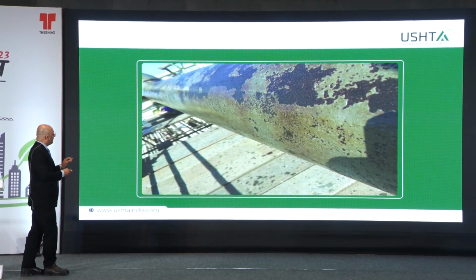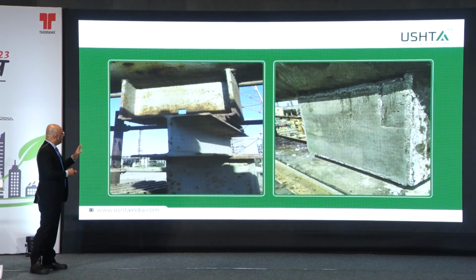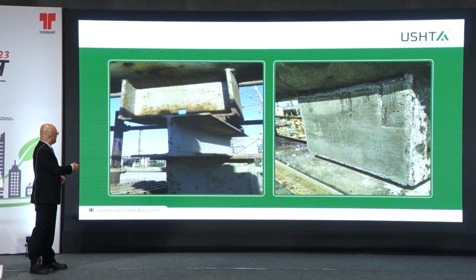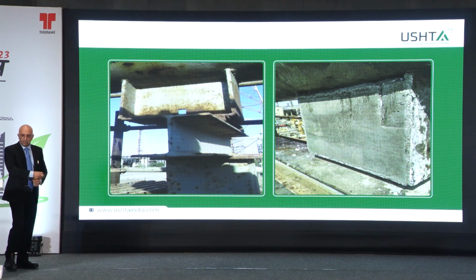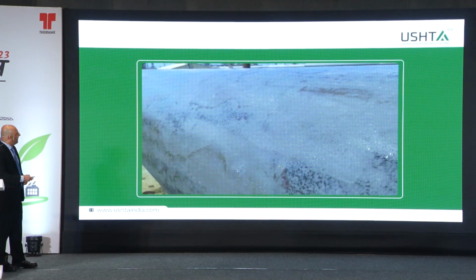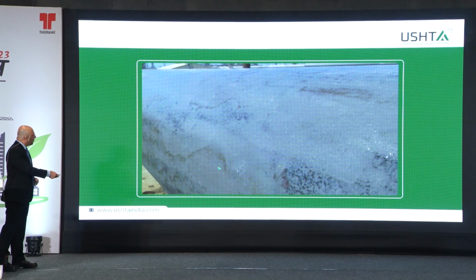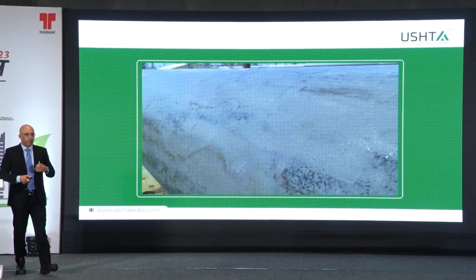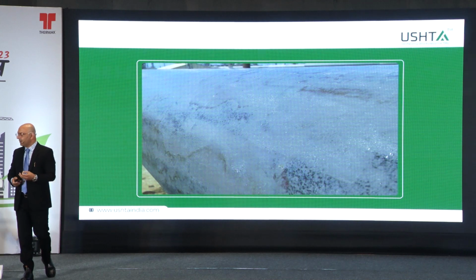And initially, all the saddle supports which were there, we filled in micro concrete and made it, so that if we wrap around this, we can easily do it without any sharp edges. And later on, we applied this putty on the top. Now, this putty is designed in such a way that because steel will have a different coefficient of thermal expansion compared to concrete.